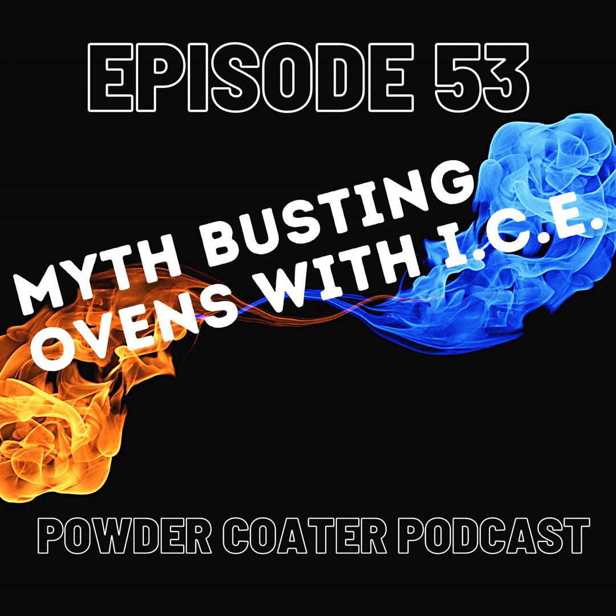what happens is, first of all, you need to use a higher grade of MDF right off the bat, because it's got to have the better resins in it that can take the temperatures. Mm-hmm. And then you have to maintain a certain humidity level within the board so that you can attract the powder to it, so you benefit from the electrostatic process. Right. So sometimes they actually will build a humidification chamber on the line, like in a process where they can actually mist, or basically sending the product through a cloud. And we used to do that quite a bit back in the day.